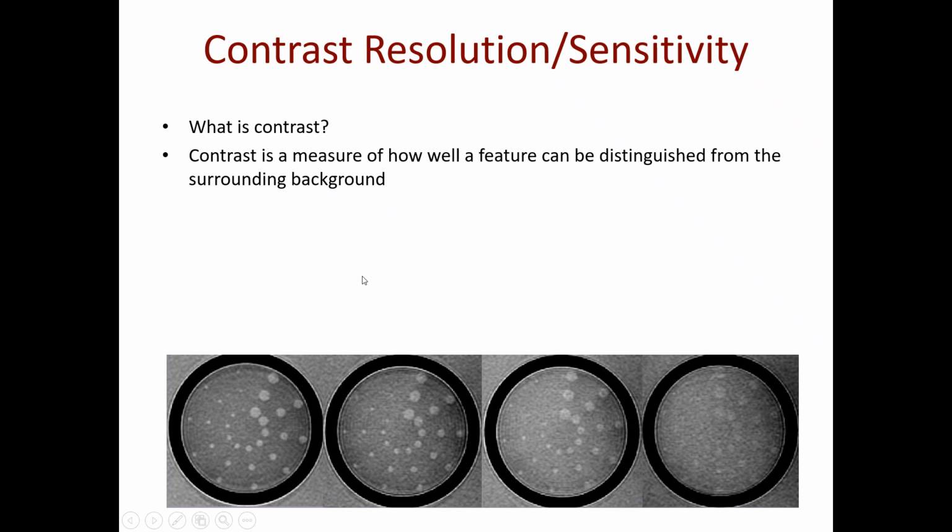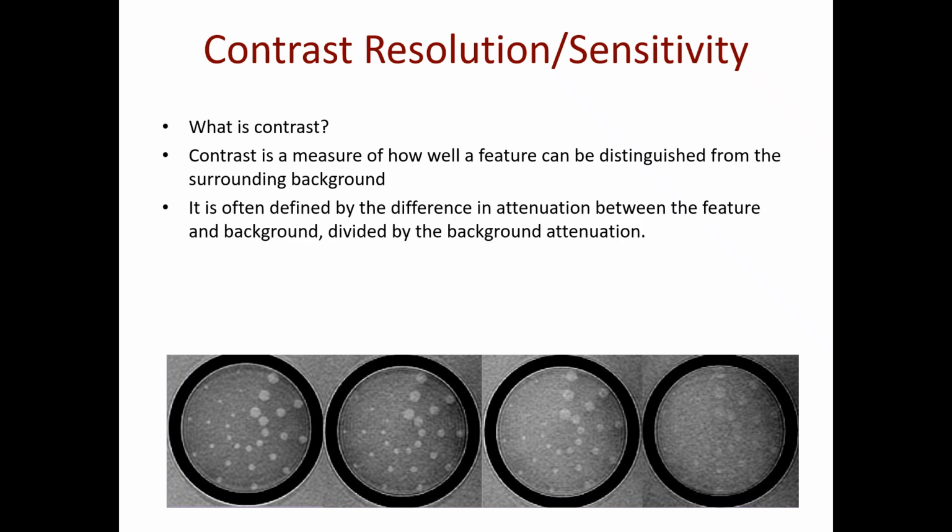I can inject my fluids with certain higher-density agents. For instance, if I have water and oil, their contrast is not good, but I can inject one of them with, for instance, iodine or bromine to increase that contrast. And then I'll be able to detect them better.